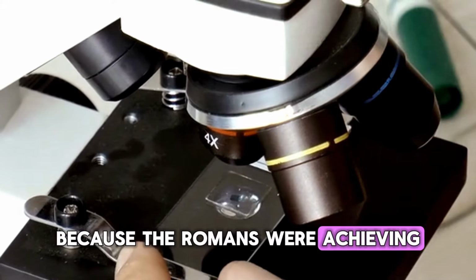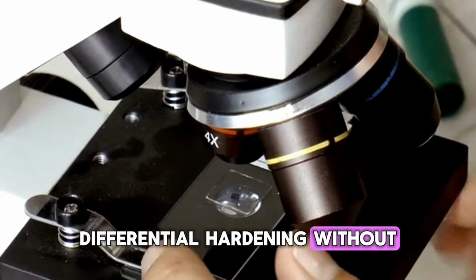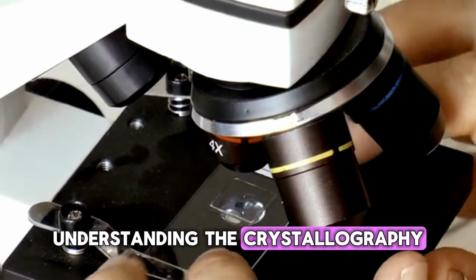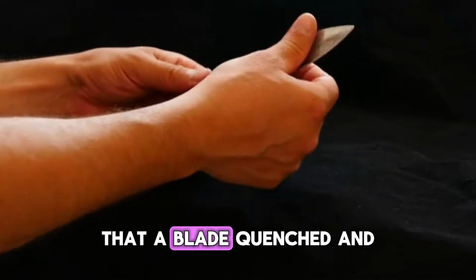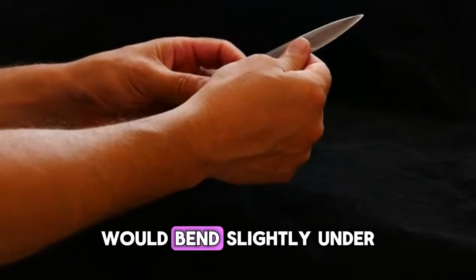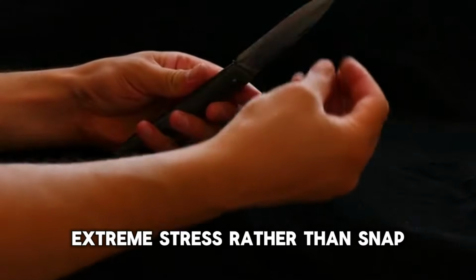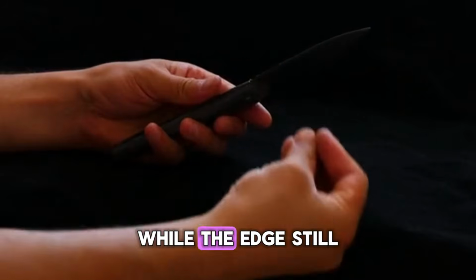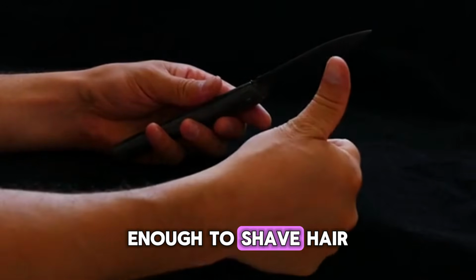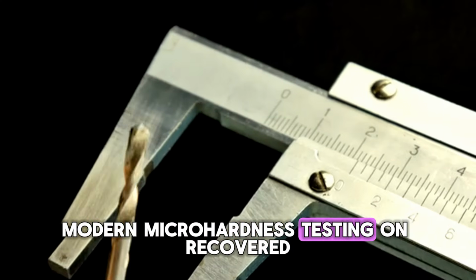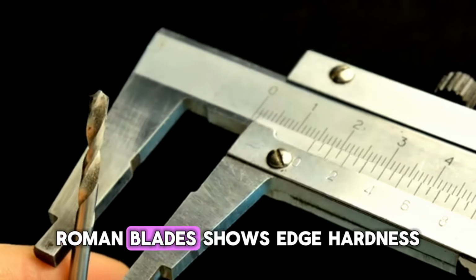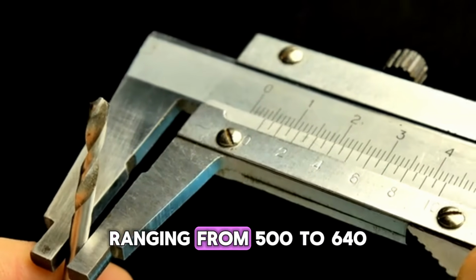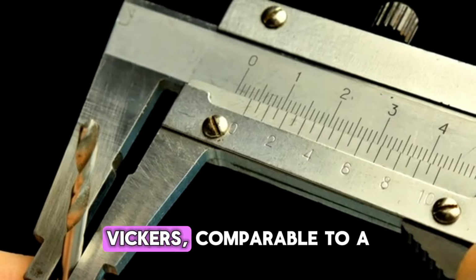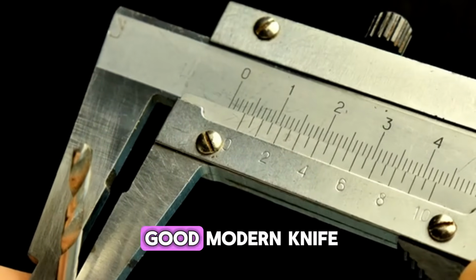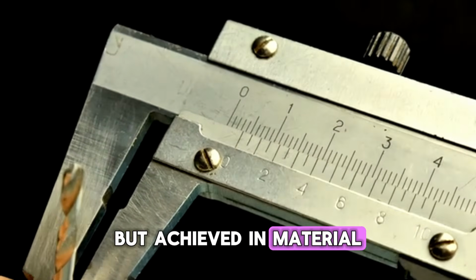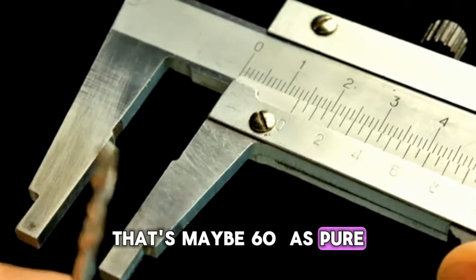Because the Romans were achieving differential hardening without understanding the crystallography. They just knew empirically that a blade quenched and tempered this way would bend slightly under extreme stress rather than snap, while the edge still tested hard enough to shave hair. Modern micro-hardness testing on recovered Roman blades shows edge hardness ranging from 500 to 640 Vickers. Comparable to a good modern knife, but achieved in material that's maybe 60% as pure.